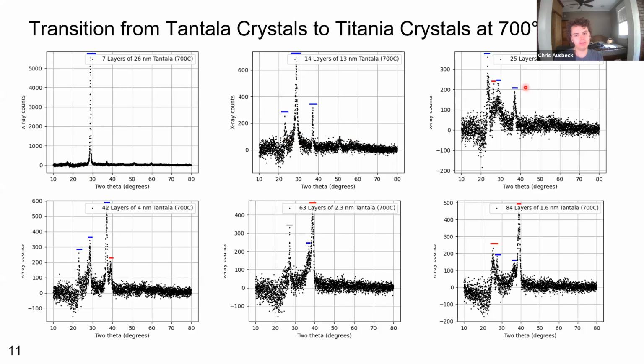Only at 25 layers of 7 nanometers do we see the emergence of one tiny titania peak around here. And at 42 layers of 4 nanometers, we see emergence of another titania peak around 39 degrees. And 63 layers of 2.3 nanometer tantala is actually the first time that we see the titania peak be larger than the tantala peak. So here we see the titania peak much larger than the tantala peak in comparison. And this gray peak here doesn't really correspond to either of those peaks.